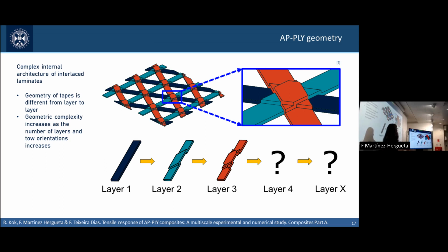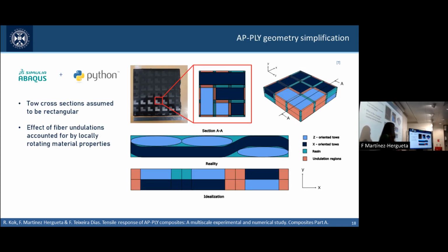But the first issue that we face is that the geometry of the AP-PLY laminate is already quite complex. When we are lining up individual tapes, we end up with undulation geometries that might not be straightforward. You might be able to predict the second layer, you might be able to predict the third. When you interlace more and more, it just gets way more complicated. So in order to conduct such research, we proposed a multi-scale model that simplifies the undulation regions, creating an idealized geometry that includes a particular undulation region that I will explain later.